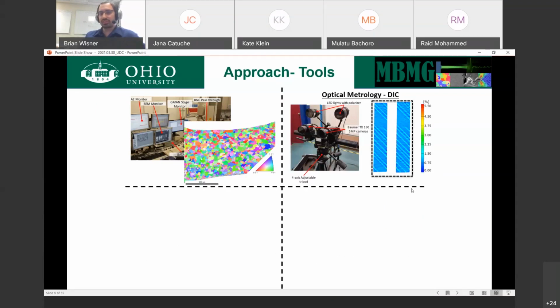We're doing this with a system that looks something like this, that's got a stereo system, two cameras. That means we can generate the entire strain tensor for this material system as it undergoes deformation, all in-plane and out-of-plane strains, which is very helpful. This particular one that you're seeing is a composite material that we are tensile loading, and you can see strain concentrations appearing as the fibers start to disbond from the polymer matrix. The top layer is oriented 45 degrees.